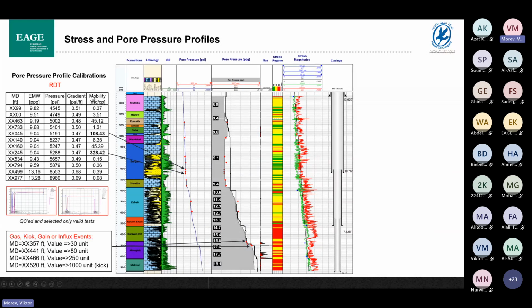So that's why in Kuwait we mostly rely on the direct pressure measurements. And here an example in the well how we put the pressure measurements directly on our pressure profile curve. For sure, we do some formation tests which show us the highest mobility, the most reliable ones. And in the intervals where we don't have the direct pressure measurements, we can rely on drilling events such as gain or influx. If we're getting gain or influx, that means our mud weight was not able to keep the fluid inside of the formation, and it's also an indication of the pore pressure which we have in our formation.